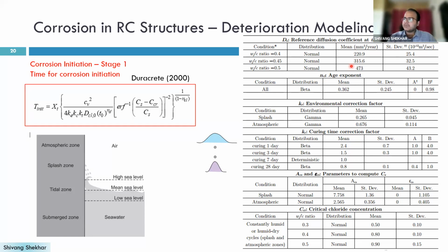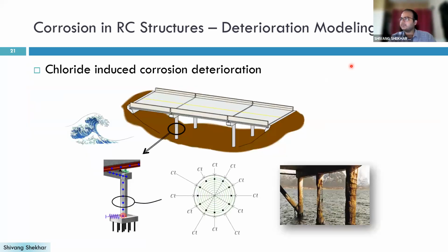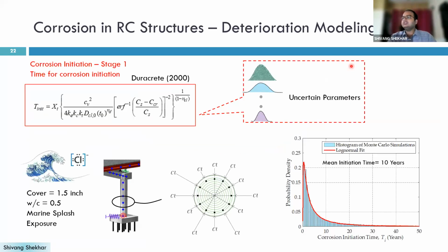So these parameters should be used in a probabilistic Monte Carlo simulation, taking the uncertainty into account, to estimate the corrosion initiation time for reinforced concrete members. What we do in our work is, suppose I have taken a reinforced concrete member, like a reinforced concrete column with a cover of 1.5 inch, that is 38.1 mm. I have assumed a water cement ratio of 0.5 and that it is located in a marine splash exposure, and so on.